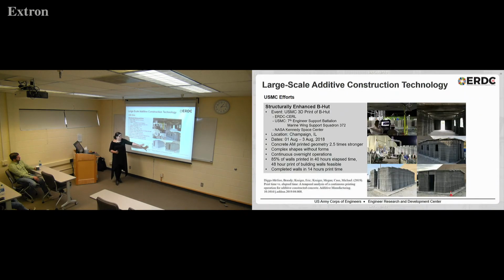And so when we did this, we tested these wall sections, and they were found to be 2.5 times stronger than straight 3D printed walls. And so when you start talking about those kind of numbers, where you can increase the strength with only about 10% more materials, if even that, suddenly you can create buildings that potentially are hurricane resistant, tornado resistant. You can create structures that are just strong and much better than what's already being made. And since we're just on the cusp of this development, this is really just the beginning of where we can go.